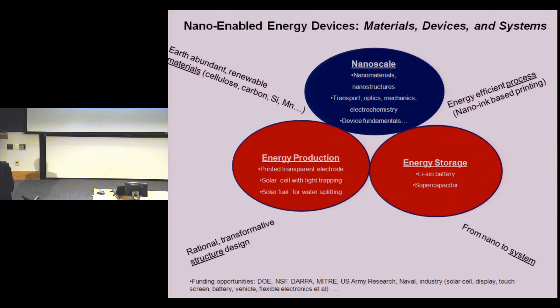Does the nature of the carbon nanotubes, like semiconducting or metallic, or diameter, affect the overall performance? Yeah, so in all these studies, we have the mixture of semiconducting and metallic nanotubes. So you always come as a mixture. So that will decrease the conductivity at the film level. And of course, we can dope the semiconducting nanotubes and make them more conductive so that you will enhance the overall conductivity of the film. Thanks.